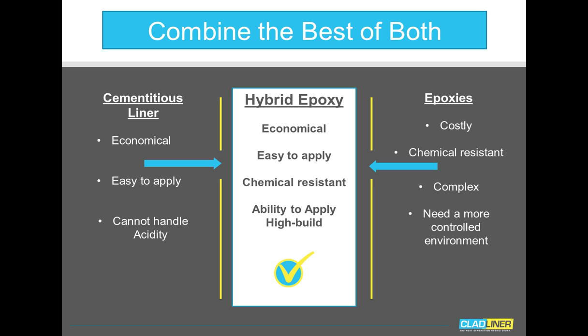Epoxies are more costly, they're more complex, and depending on which polymer type you're applying, they often need a much more controlled environment. However, they are more chemically resistant and as a result more long-term. So, if we put those best features together, we come up with a hybrid epoxy or epoxy-modified mortar. We have a product that's a lot more economical than a traditional epoxy would be. It's much easier to apply. It's chemically resistant, as we saw in the study, and it can be built as a high-build liner.